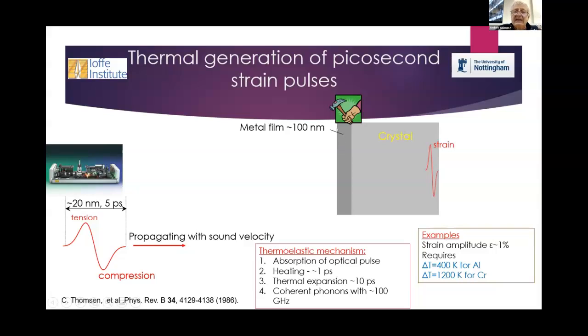This is the simplest mechanism, the so-called thermoelastic mechanism: the film expands and strain is generated due to heating. The amplitude may be quite high, about 1%, but it requires very high temperatures—for aluminium film, heating up to 400 K, and for chromium even more. So people usually push up the amplitude until they eventually destroy the film, leaving a hole, and nothing works anymore.